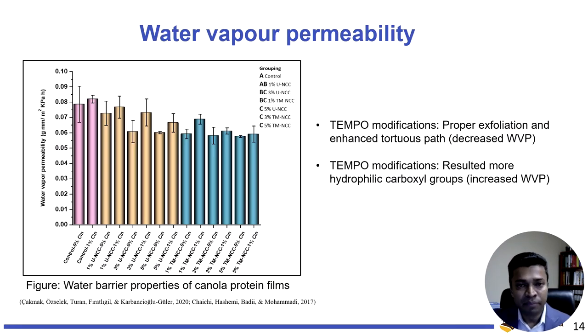Then the other thing we wanted to look at is the water vapor permeability. So TEMPO-mediated oxidation did not make a significant change in the water vapor permeability. There was a little bit of reduction, but at the same time, it's not what we expected or wanted. The reason is that even the TEMPO-mediated oxidation is still a hydrophilic reaction. We are replacing hydroxyl groups of the nanocellulose with carboxylic groups. So that's the reason why we did not see a huge improvement in the water vapor permeability.